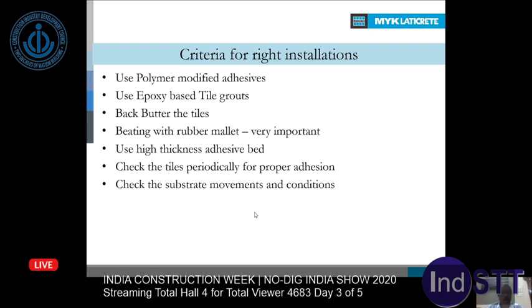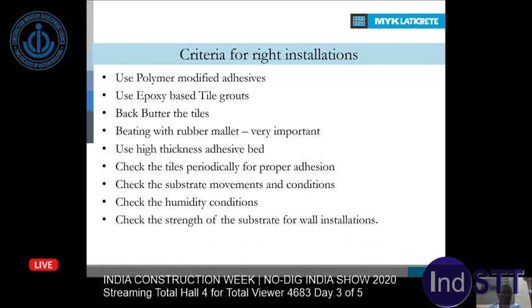And make sure when you are fixing, the substrate movements and conditions are very, very important. Accordingly, select the right tile adhesives. And humidity conditions are also very important. That helps on the curing. And it's very important that suppose you have a very high strength adhesive material, and your substrate is very weak, something like a plaster or paint or your hollow blocks, then what happens? The substrate will cave in, because the high strength material will have good adhesion to both substrate as well as the tile, but the substrate can break, then the whole installation may come down.